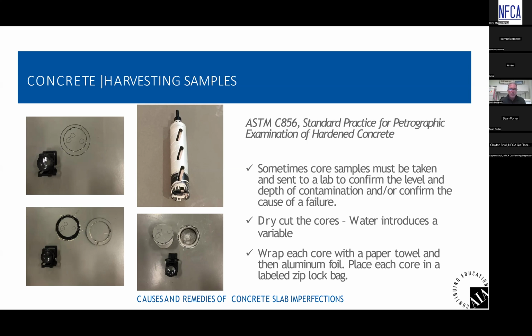As soon as we harvest the core sample, we wrap it in a paper towel, wrap it in aluminum foil, and then put it in a Ziploc bag and send it off to the lab. Typically do a minimum of 3 cores is my recommendation. 1 core could be an anomaly. 2 cores could have 1 anomaly, and you only have 1 good data point. So we should do a minimum of 3 cores.